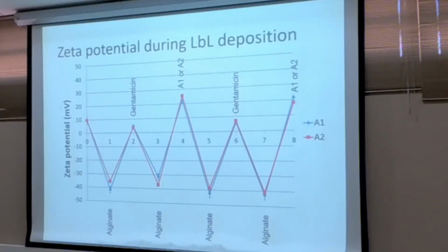Another aspect when we do this layer-by-layer deposition: we wanted to ensure that our zeta potential changes when we create the layers, because we have to make sure that our next layer sticks to the nanoparticle. That's why, every time we put on one layer, we measure zeta potential.